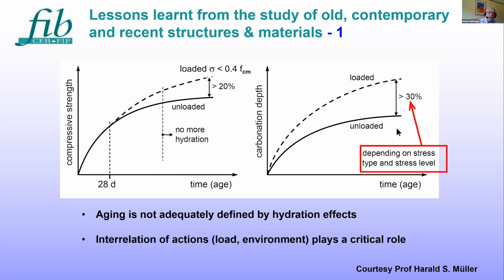The graphic on the left deals with compressive strength of concrete versus time. The development of strength over time is also affected not only by hydration, but also by loading effects. So an unloaded structure or a loaded structure can have a different in situ compressive strength. And you'll see from the graphic that a loaded structure may have 20% more compressive strength. If you look at the graphic on the right, carbonation depth versus time, you'll see again that highlights loaded and unloaded experience. So the behavior and the depth of carbonation is dependent upon the stress type and stress level. So loaded structure with more microcracking, the carbonation depth is likely to be appreciably more than in an unloaded structure.